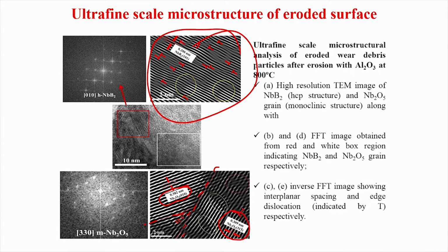So, in this particular range, you can see that there are lines along this line, this edge dislocation, and these edge dislocations essentially are the signatures of the dislocation activity in these materials of the eroded surface. So, all in all, this combination of the dislocation activity as well as Nb2O5 phase formation essentially indicates that erosion experiments at 800 degrees Celsius cause measurable oxidation and also noticeable dislocation activity, and it is quite plausible that dislocation plasticity reduces the wear of these materials, in contrast to micro cracking induced spalling, which commonly takes place in the case of brittle ceramics. So, these are the 2 things that are really important in this particular case of ceramics.